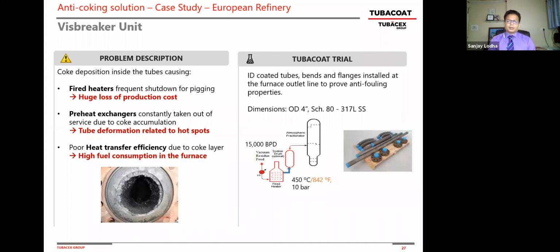Then they have a pre-heat exchanger upstream of the furnace that is also taken out of service due to coke accumulation, and a poor heat transfer that gives you a higher fuel consumption. So they agreed to go with the Tubacoat solutions, 4-inch diameter, inner coating, schedule 80, 317 stainless steel, and also the flanges and the bends. We supplied that. Next slide, please.